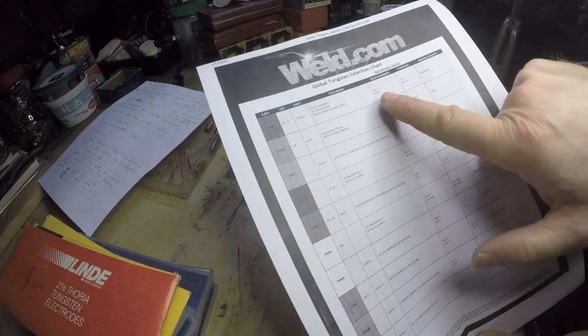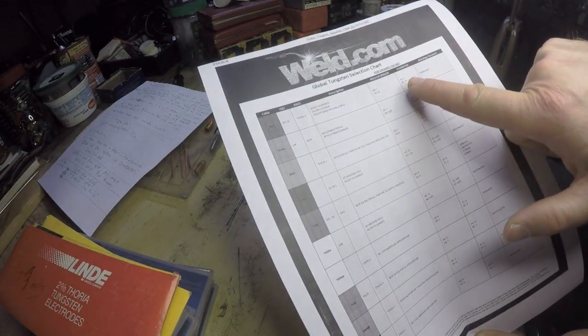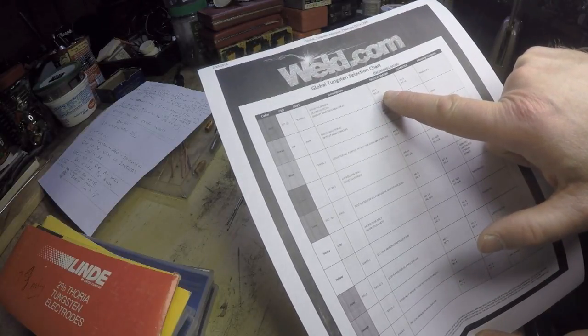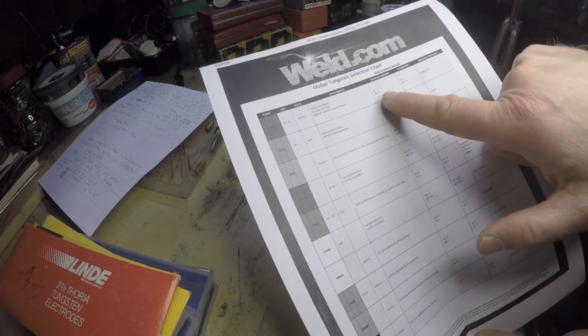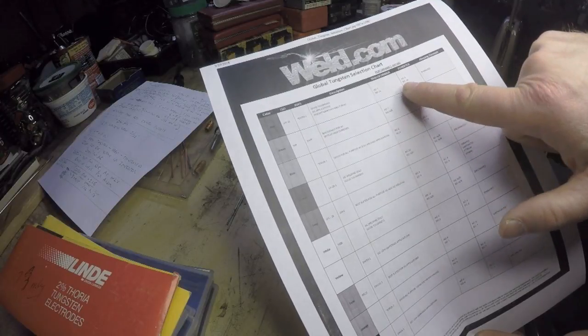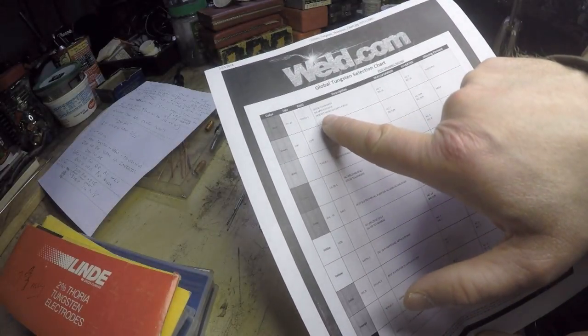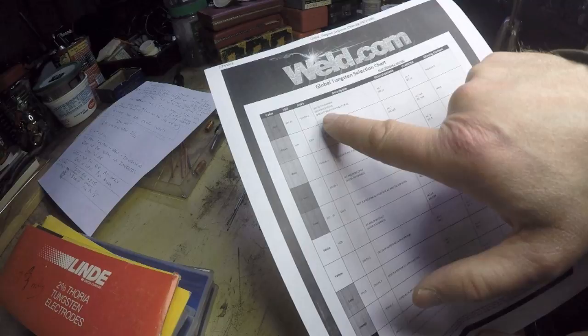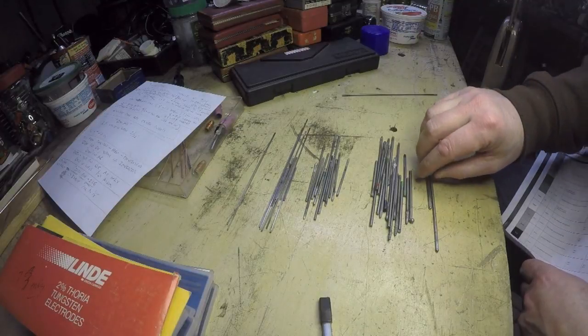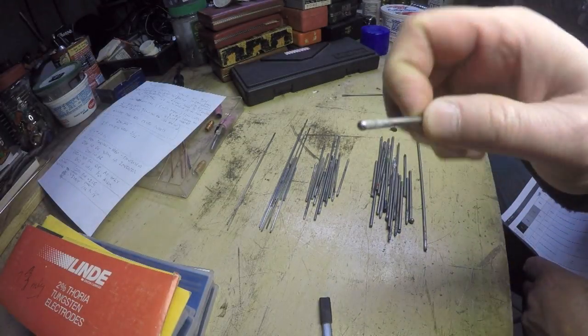And so when I look at the really popular ones here, red, they give it a 10 on either a transformer or inverter welder when used on DC. So that would be for your mild steel. It'd be an excellent electrode for mild steel. They only give it a 7 on AC for a transformer welder, and it's even lower, a 5, for AC on an inverter welder. And what they say is, it's got good toughness for DC applications, but it doesn't maintain a ball for AC. So when you AC weld, you actually want to get the tip to ball up like this. What they're saying is, yeah, no good for that.